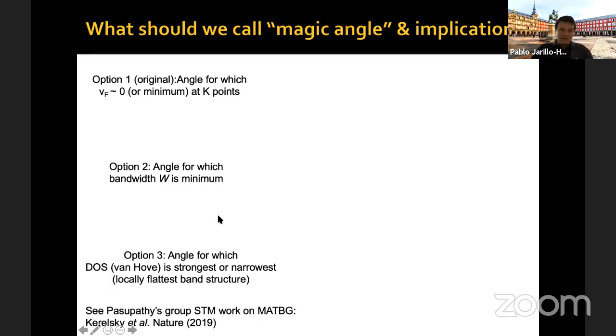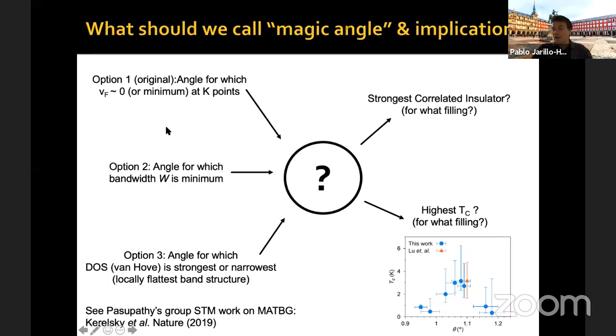Okay, that last definition was, for example, argued by the group of Abhay Pasupathy in the recent STM work. Now the thing is, we don't know yet theoretically how any of these definitions, or others that we may come up with, correlate with the type of behavior that we observe in these devices, okay? For example, should we name magic angle the one for which the strongest correlated insulator states appear? And for what filling? Because different numbers of electrons per moiré unit cell show different strengths of correlated insulator physics. Or should we choose instead the angle for which the highest TC occurs, okay? And how do these properties, and many others that are being discovered now, connect with these possible theoretical definitions of magic angle, okay?